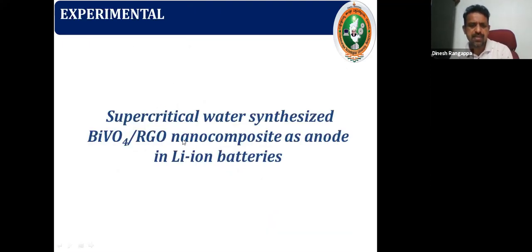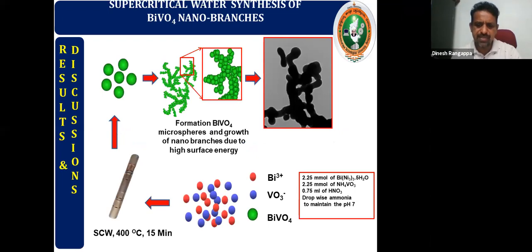So similarly, bismuth vanadate, two papers, and bismuth molybdenum oxide and RGO composite were published, and now bismuth vanadate and bismuth tungstate are under submission. Here, bismuth vanadate shows formation of microspheres under supercritical condition, where these microspheres convert into nano branches like this, and